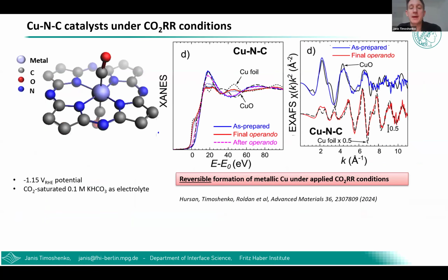So if you look at what happens with this copper NC catalyst under applied negative static potential, again, even if you're not an expert in X-ray absorption spectroscopy, just by looking at the spectra and comparing them with the spectra for references, you can see immediately that in the beginning you have some sort of oxide-like or cationic structure, which might have a similar local environment as copper in copper oxides.